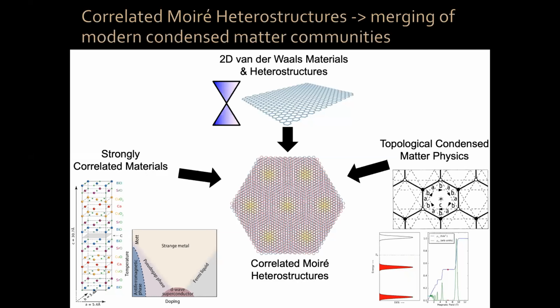The type of measurements that, for example, were done in the cuprates to demonstrate d-wave, right? ARPES or phase sensitive measurements in a SQUID geometry. Those are much harder to do for magic angle graphene. With ARPES, the flat bands have such a small bandwidth that it is below the resolution of ARPES to see the details of the electronic structure. So we need improvements in ARPES, both in temperature and energy resolution.